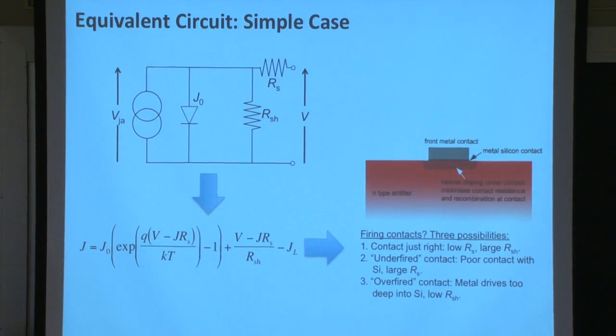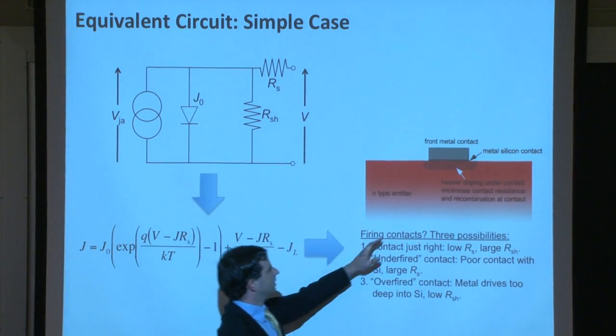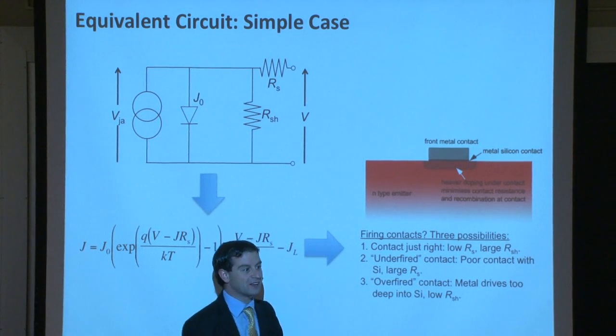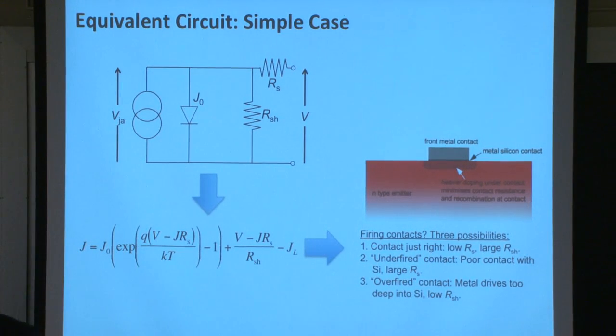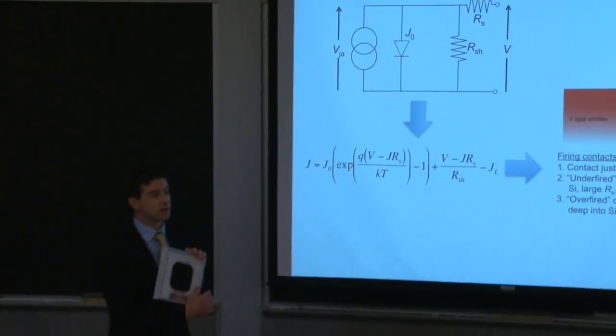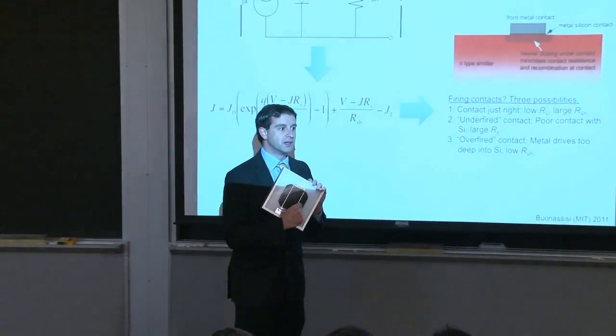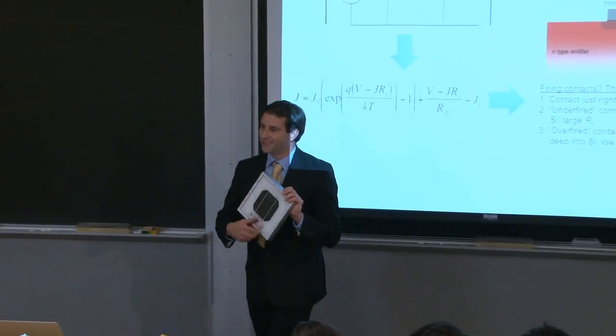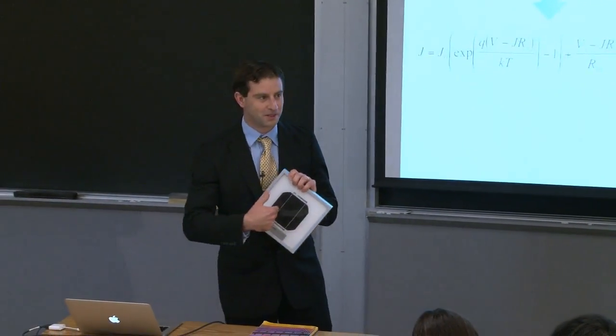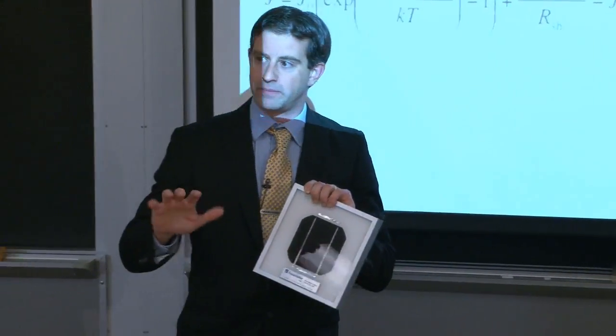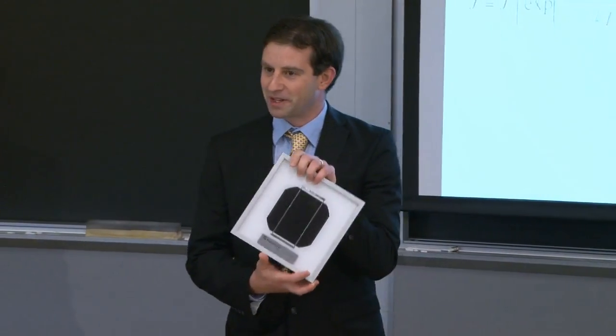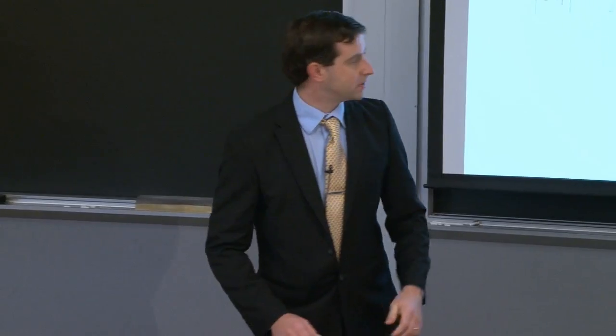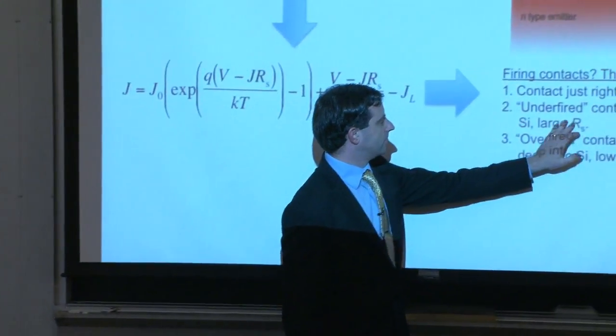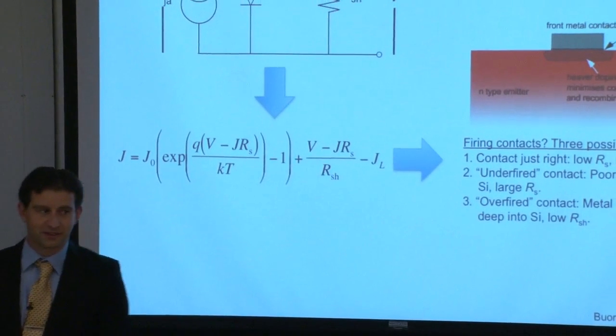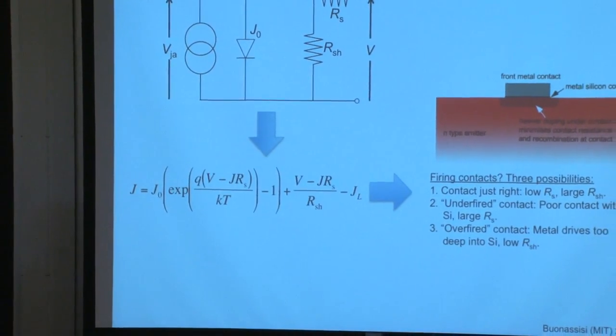What does a shunt mean? A shunt means that the metal goes straight through the p-n junction and contacts the base material on the other side. So remember, the p-n junction region of the solar cell is only about a micron away from the surface. It's really close. So if you have a fast diffusing metal species and heat it up too much, you'll get the metal going straight through the, in this case, the N+ layer into the P. You'll shunt your device. So this is the fine balance that you have to walk when you're putting contact metallization on a device. You can't overfire it because you wind up with shunts. You can't underfire it either because you might wind up with a very large contact resistance. So it's a very tricky thing to get right.